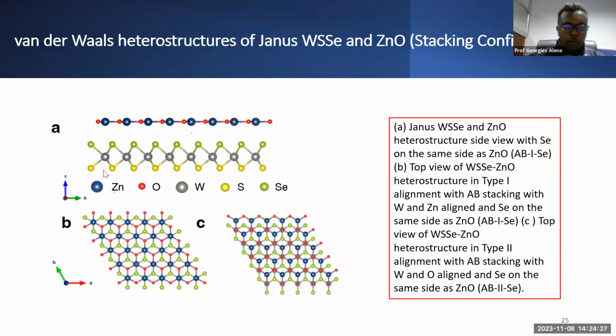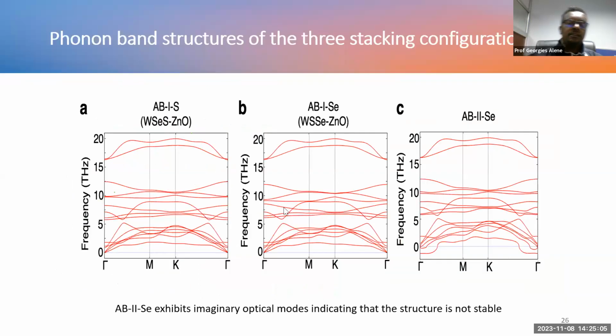So this is how we make the heterostructure. For example, here we have WSSe on the bottom, and on the top we have zinc oxide. So this is a side view, and B and C show you a top view. So depending on the alignment of, for example, the zinc and the tungsten, how it is shifted, we can have different types of stacking patterns. And as I mentioned before, we have selected three of them out of the 8 high symmetry stacking patterns and studied them. The first thing we have done is we calculated